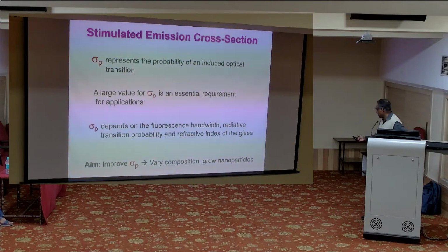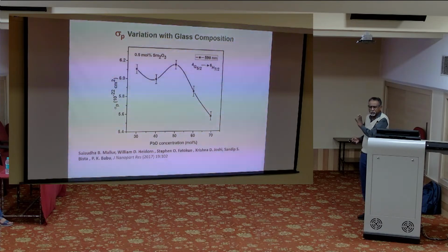So like that, our idea is to improve this particular quantity known as stimulated emission cross-section by playing with the composition of the glass. So we have seen that deriving this quantity takes a lot of time, analyzing all the optical absorption, fluorescence with a lot of computer programs. So we show that with the lead oxide concentration, you can see that there is a peak in the stimulated emission cross-section. So at a particular value of the composition, the glass is most efficient in producing fluorescence light. That is one of the most important conclusions from this particular work that we have done.